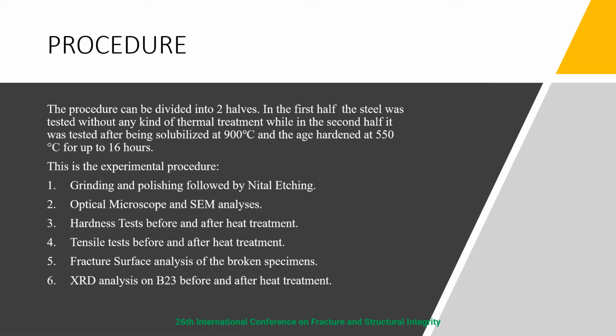Now coming to the procedures, they can be divided into two halves. In the first half, the steel was tested without any kind of thermal treatment, while in the second half, it was tested after being solubilized at 900 degrees Celsius and age hardened for 16 hours at 550 degrees Celsius.